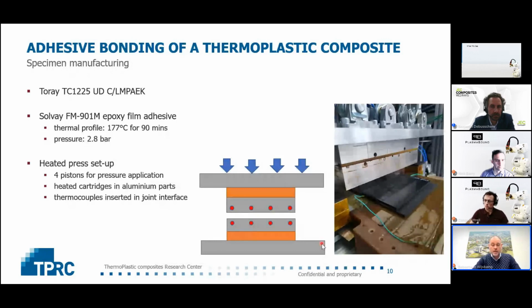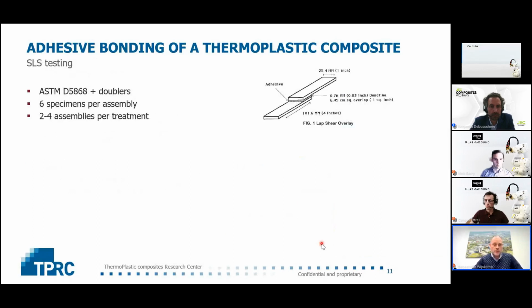So it's a relatively quick way of co-curing materials, so no complex buildup in the autoclave, for example. Might have some disadvantages, but for a quick scoping study it worked. So we used this heat press setup with control through thermocouples. Then we cut single lap shear specimens according to ASTM D5868, including doublers. We usually prefer fracture toughness based testing, like the double cantilever beam or mandrel peel test. The double cantilever beam test was introduced by Nick earlier. But as a first scoping method, the lap shear test works very well, and people can quite easily relate to a lap shear strength.